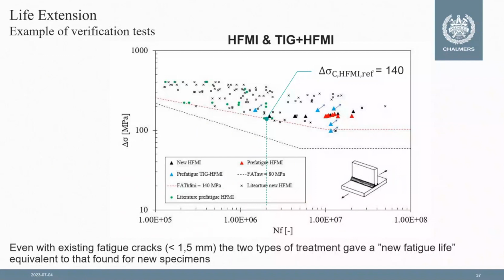The results can be shown in different ways. What we see here is the conventional SN curve, and we see new HFMI treated details without any pre-fatigue. These are the crosses. And then we see the triangles and the green circles, which are pre-fatigued details that, after crack initiation, were treated with HFMI. In all these cases, the cracks were less than 1.5 millimeters deep, rather long in length, but through the thickness less than 1.5 millimeters. Even in such a situation, the HFMI treatment resulted in an extension of the fatigue life similar to that obtained for a new welded detail, HFMI treated, which is extremely good, of course. All test results fall above the SN curve 140, which is for this detail in a new condition.